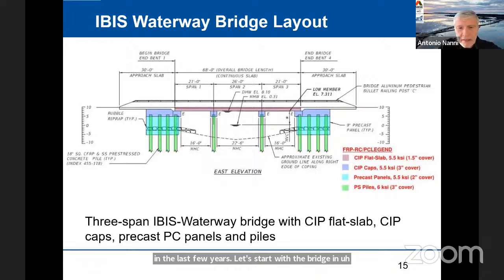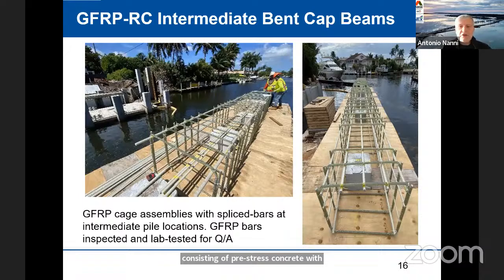This bridge is certainly interesting for the items that you see in this picture, colored in pink and purple, and they are the cast-in-place deck as well as the pile caps. This bridge was only built with non-ferrous materials, but I'm not going to go into the elements consisting of pre-stressed concrete with carbon FRP tendons. Here in this picture, you see the cages, so nothing different from what you do in the case of steel, other than the workers love it because of the lightweight of the material. The weight of GFRP is approximately 1/4 that of steel.